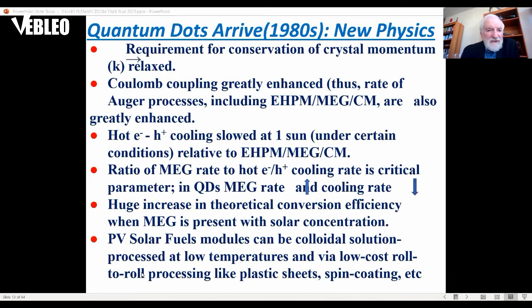So what changed was the new physics that became apparent in the 1980s, which showed that when you go to very small particles in the nanoscale regime, small particles of semiconductors, you have many effects which are very important for solar energy conversion. One is you relax the requirement of conserving momentum, because momentum is not a good quantum number, because according to the Heisenberg uncertainty principle, there's an uncertainty if you multiply the velocity times the position. And since you know the position, because it's confined to a small region of space, you don't know the velocity, which means you don't know the momentum. So you don't have to conserve momentum as you do in the bulk.